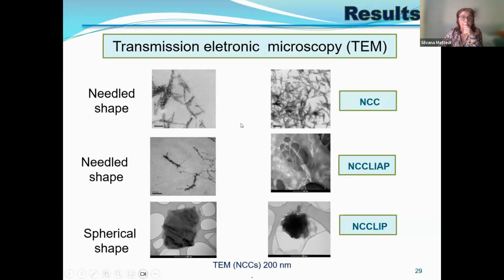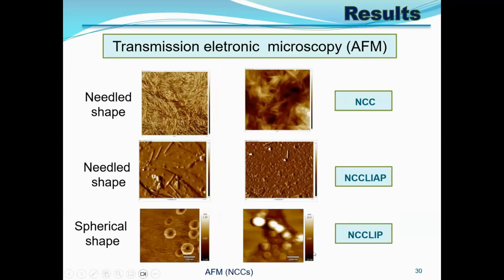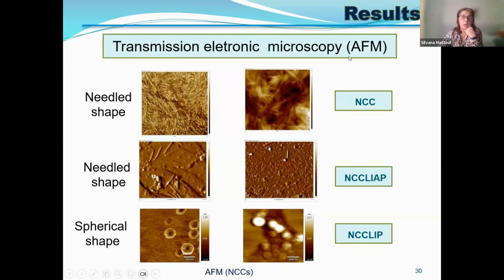We did transmission microscopy, and what we see is that we have different materials for the nanocellulose. For sulfuric acid, you have a crystal needle shape, and also a needle shape for imidazolium, and a spherical shape for protic ionic liquids. The same we can observe with atomic force microscopy.